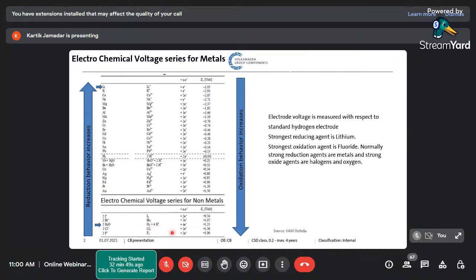Then chlorine, which was giving 1.36, was also out because of toxicity, and at the same time a very high affinity to lithium. And then came oxygen and water. We know that hydrogen is zero. The potential for water, the oxygen part of it, was 1.23. And that is our starting point for the cathode. They started realizing that oxygen could be a very good cathode material. That is how the first battery started, with lithium oxygen batteries.